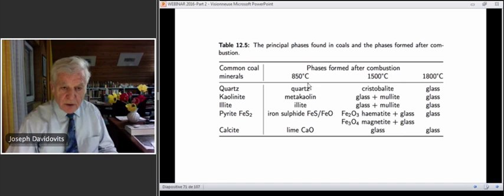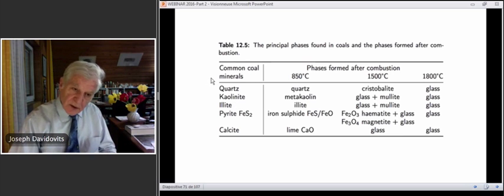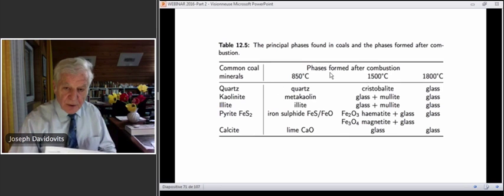This is an excerpt of my book, table 12.5. In common coal minerals, coal, that is the constituent that will produce fly ash, is made of carbon, of course, and then quartz, clays, kaolinite, illite, pyrite, FeS2, and calcite, calcium carbonate. And these minerals will undergo transformations depending on the temperature of combustion. At 850 degrees C, you get quartz, no change. Kaolinite is transformed into metakaolin. Illite is illite, no change. And pyrite is transformed into FeS, iron sulfide.